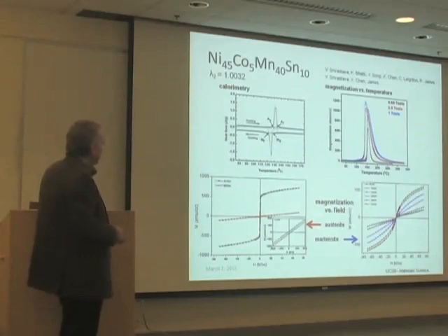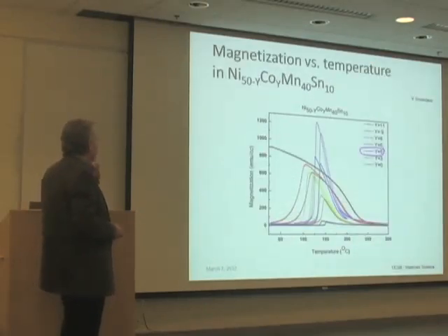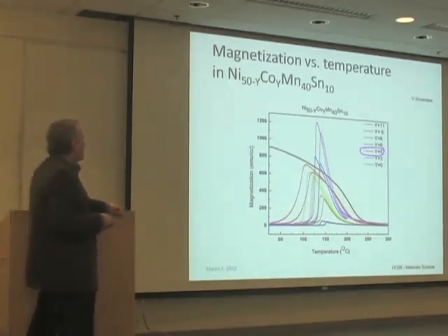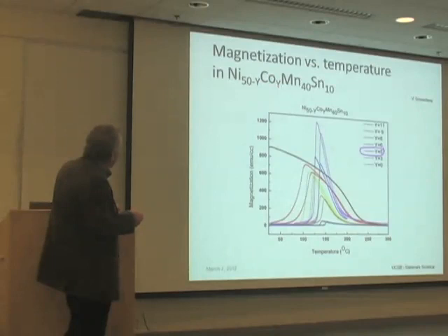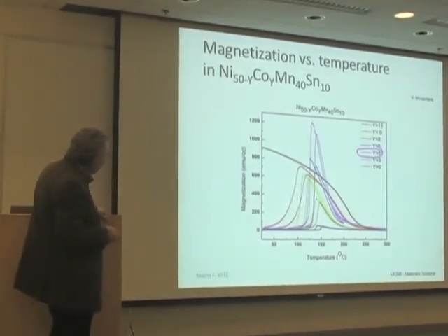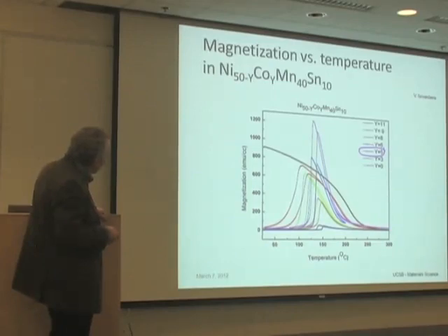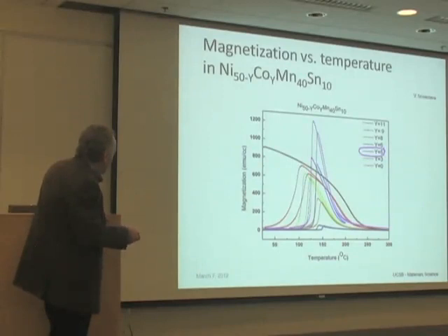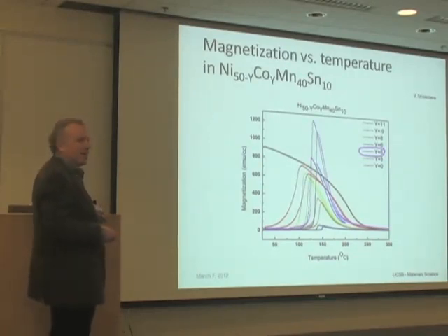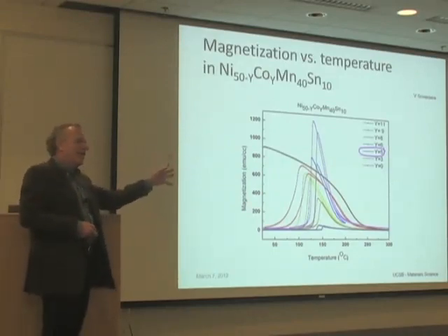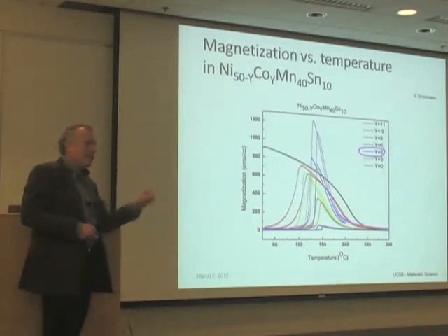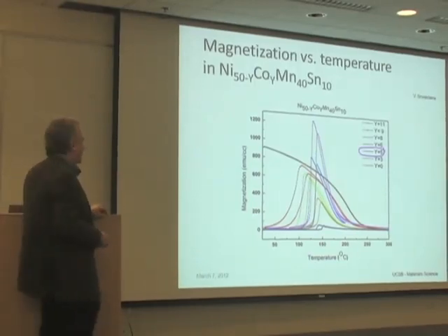Here's something that totally blows my mind. Nickel, cobalt, manganese, tin. Y is the percentage of cobalt. The alloy I was just showing you was Y equals 5. That's that alloy. You change 2 percentage points down to 3, and it drops off almost to half in the magnetization. You change 1 percentage point in the other direction up to 6, and I'm sorry, 6 is this one. It's about half. 3 is down here at about a third. So you have 100 unit cells of this material in front of you, and you pluck out one nickel and you stick a cobalt there, and the magnetization changes by a factor of 2. How could that happen? So anyway, it's really something interesting on the basic magnetic side to understand.